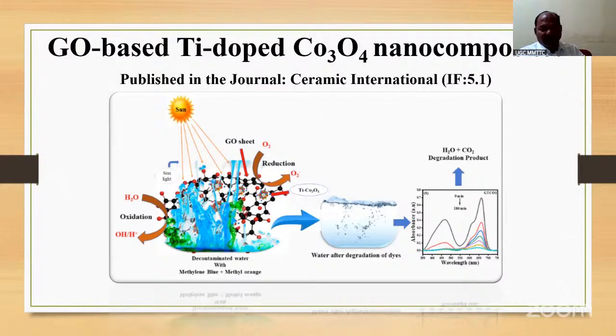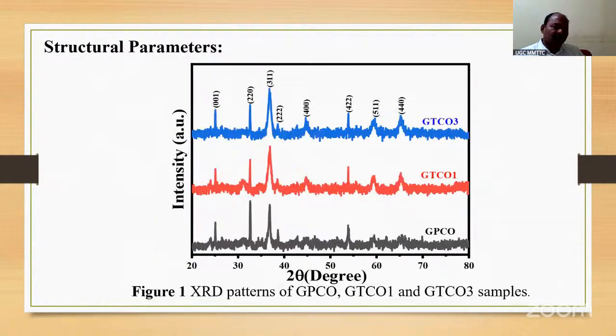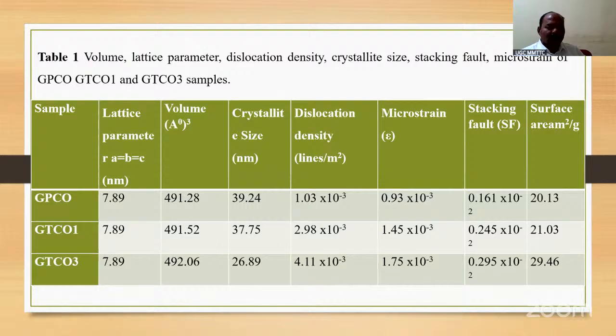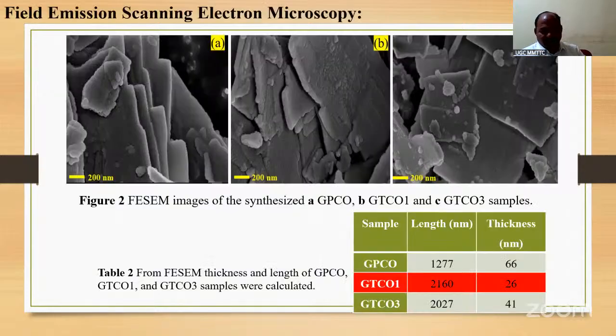And now you see here the degradation product. We got the material and XRD here. It is very interesting again. For this we successfully synthesized and got the micrographs. See here the slab-like sheets, two-dimensional materials, films and sheets. At 200 nanometers, the length of this is 2160 nanometers. The thickness is lesser, but the length is higher.